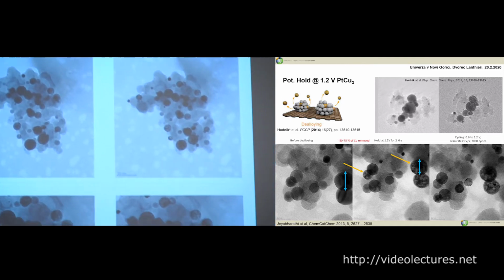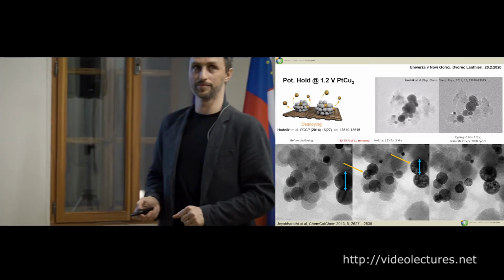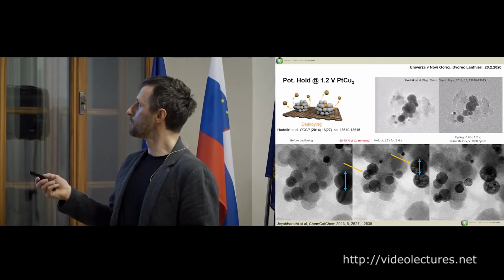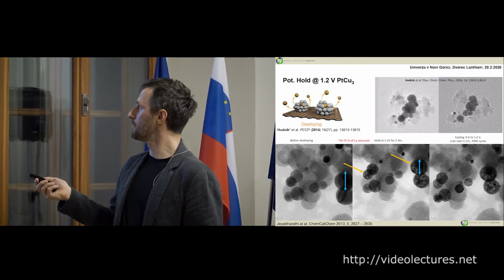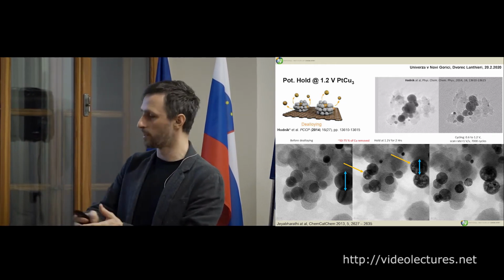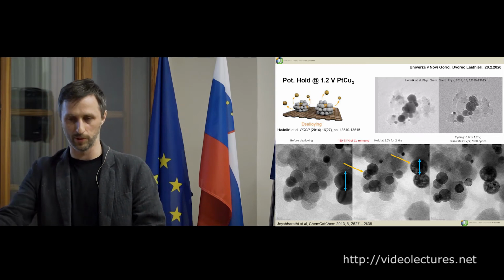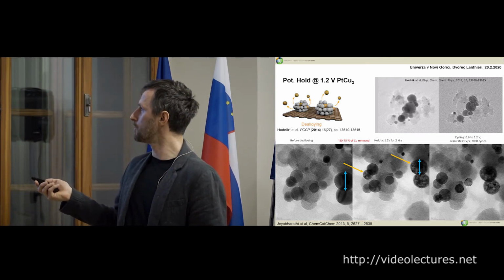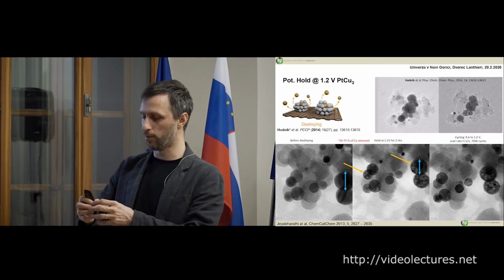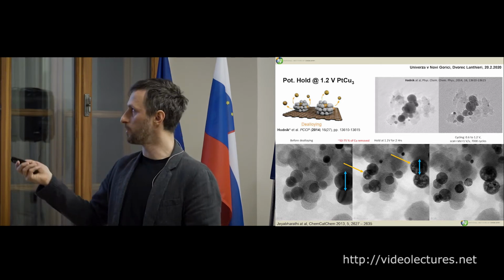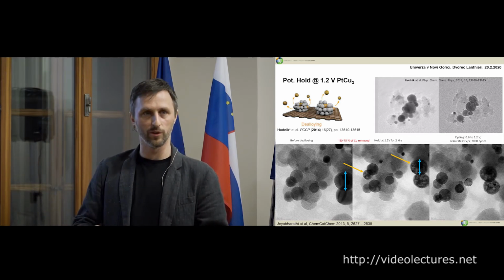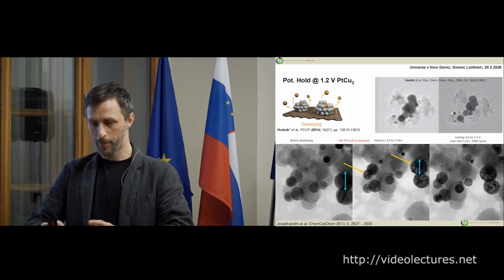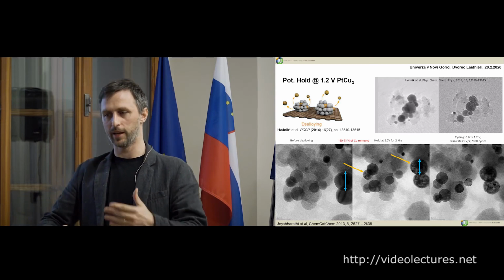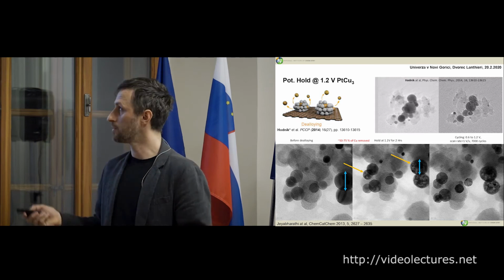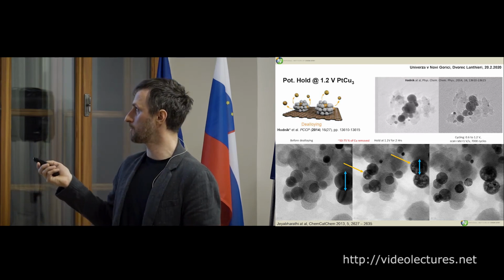Now here are more images. Now we show a lot of images. So what we see here is again porosity. What's interesting here is that if you do the degradation more, so you expose these potentials, you actually see the porosity coarsening, so the pores grow. So it means when you make pores, it's not the end of the story, they also change. They grow, and this is then the mechanism where you lose surface area. So the surface area of this one is higher than this one.